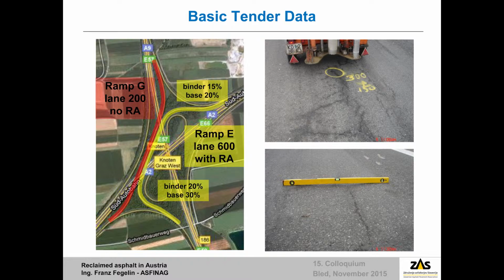Ramp G, which you see here in red, was made using traditional asphalt mix, so without reclaimed asphalt. Ramp E, which is marked here in yellow, was divided into 2 sections. One was made using 15% reclaimed asphalt for the binder course and 20% for the base course, and the other half was made using higher percentages, 20% in the binder course and 30% in the base course.